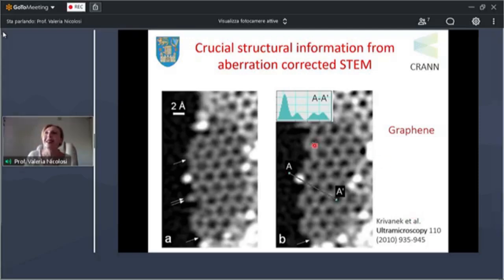In this case, this is an aberration-corrected scanning transmission electron microscopy of the same graphene sheet a few seconds apart. These two electron micrographs have been taken, and you can see a lot of adatoms, a lot of dangling bonds. You can see a lot of defects. Here is a 5-member ring, and so forth. In this case, actually, the structure rearranged itself into an armchair type of edge a few seconds later, cleaned up basically with the use of the electron beam. All we learned here is that the material was not perfect at all.